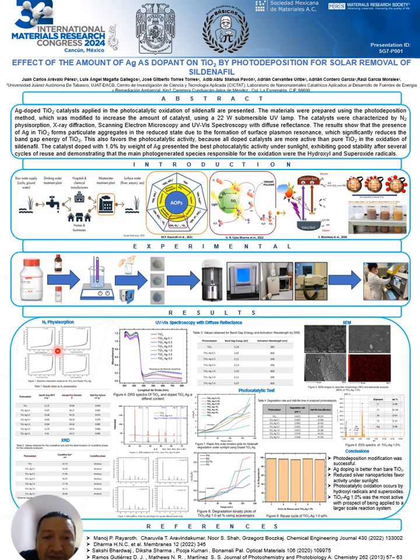The results show that the silver doping doesn't significantly affect the specific area, diameter, and pore. Only the anatase crystalline phase was identified in all materials and the crystal size did not show significant change. The samples with the highest silver content exhibit a small signal attributed to cubic silver oxide.